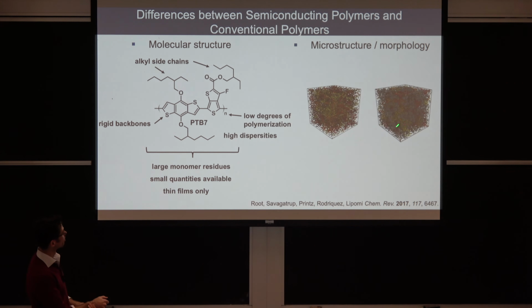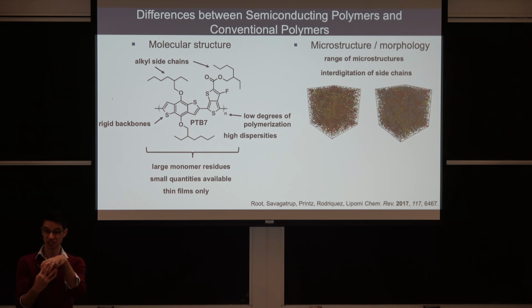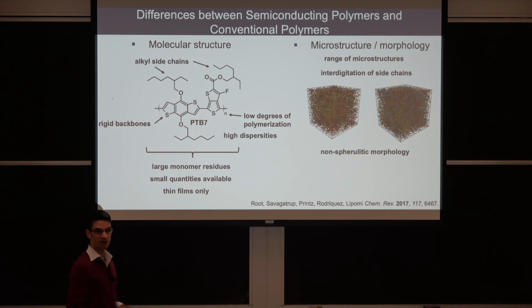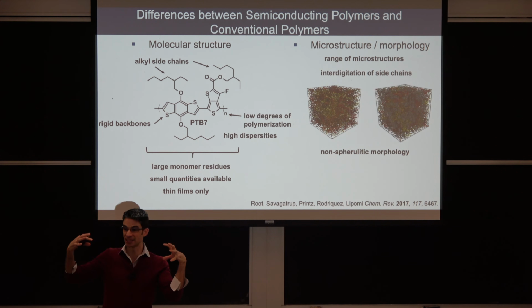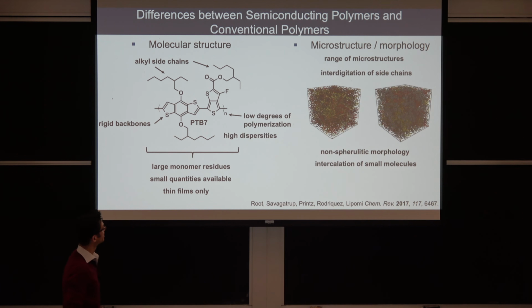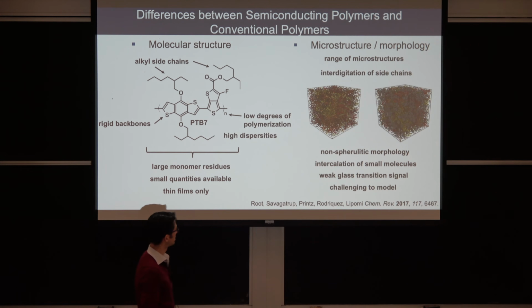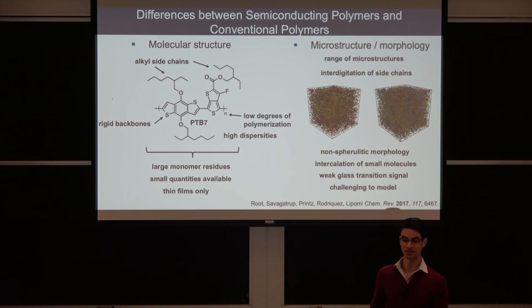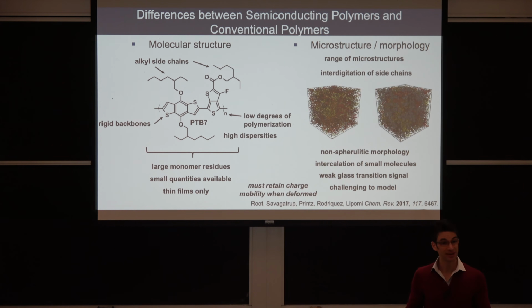Now, if you look at the microstructure and morphology, so this is nanostructure, even molecular packing structure, we have a range of microstructures available. We can have these side chains that interdigitate on the nanoscale. You can have non-spherulitic morphology, so these spherulites, kind of these three-dimensional snowflakes that occur in most polymers, don't really occur here. You could have intercalation of small molecules, like small molecule additives, in between the side chains, which can complicate your analysis. You generally have a weak glass transition signal by calorimetry, and they can be challenging to model, although I'll tell you a little bit about some of the modeling efforts that we've made. Critically, compared to polystyrene, these materials must retain their charge mobility when deformed.